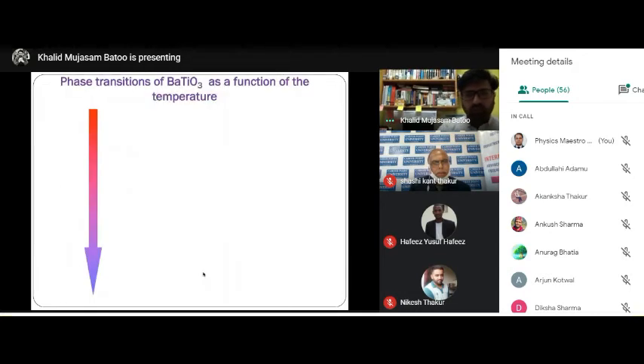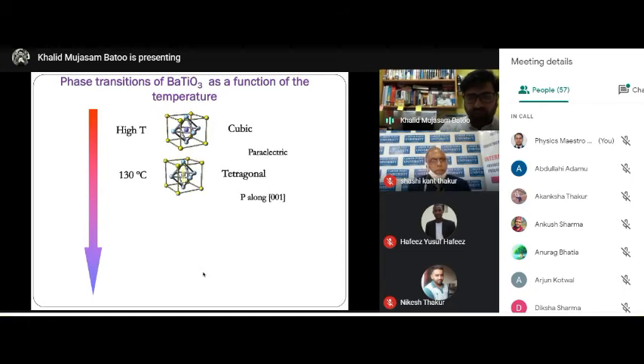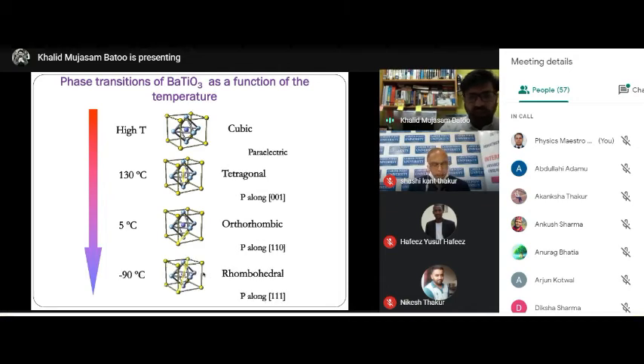What happens as we play with the temperature? Temperature is an important aspect in barium titanate. At high temperature it's cubic paraelectric. At 130 degrees centigrade it is tetragonal, at 5 degrees it's orthorhombic, and at -90 degrees it's rhombohedral. So you see it is changing structure with the change of temperature.